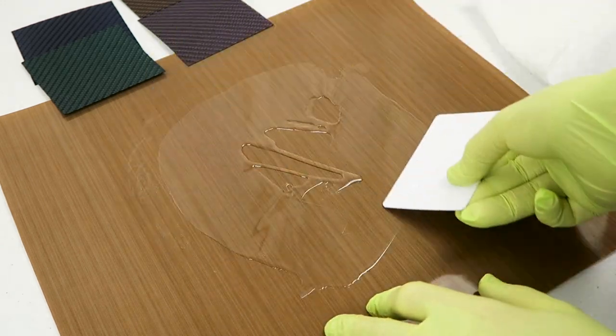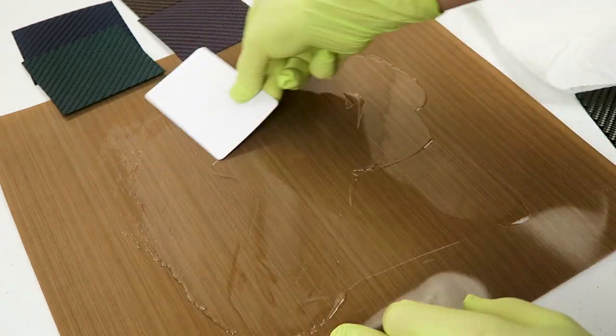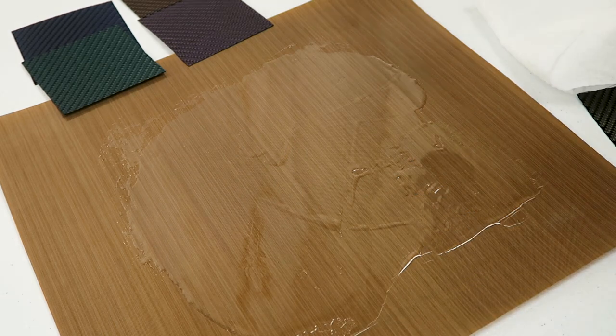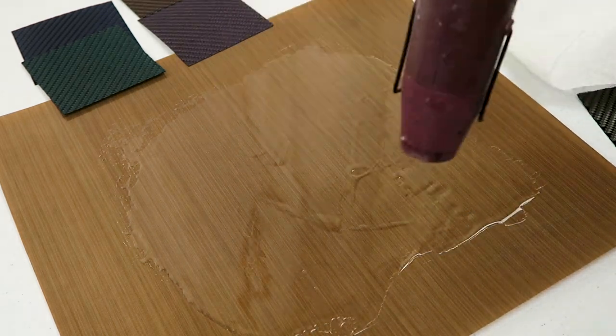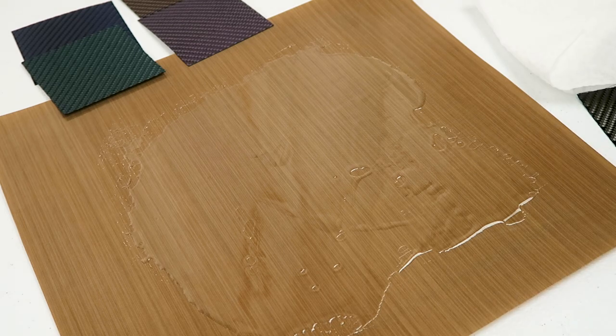This epoxy resin has been degassed in a vacuum chamber, and then once it's spread onto the sheet of Teflon peel ply, I still used a heat gun to pop any bubbles that I added in while applying the resin to the sheet.